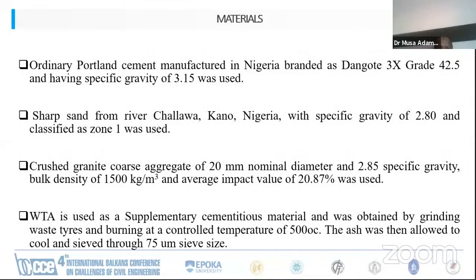So the materials used here are ordinary Portland cement obtained from Nigeria with a specific gravity of 3.15, with a sharp sand from Kano, Nigeria with a specific gravity of 2.8 and classified as zone 1. Then crushed granite of 20 millimeter maximum nominal size and specific gravity 2.85, bulk density of 1,500 and impact value of 20%. Then we use the waste tire ash as supplementary cementitious material, and it was obtained by burning the waste tire at a controlled temperature of 500 degrees, allowed to cool and sieved through a 75 micron sieve.